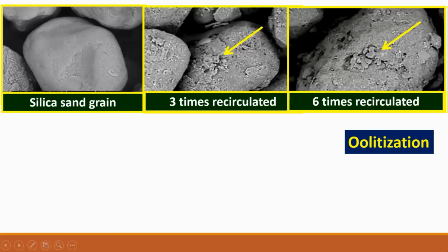You know how this is called oolitization. They become oolitics. The oolitics are again porous. These deposits on the sand grain are very porous and then they absorb water. So that is another negative aspect. But they also provide some cushion to an extent when you can accommodate some amount of this oolite on the sand. They will provide a cushion for expansion of the sand. But beyond a certain level, they become a nuisance by absorbing too much moisture.